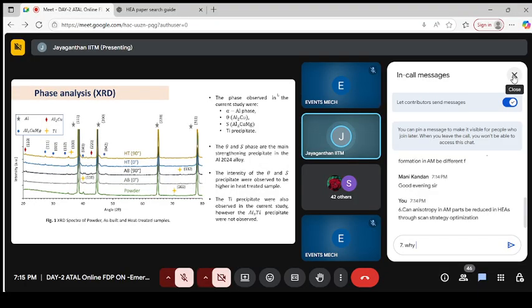And then if you do X-ray diffraction, you can see at the bottommost. We have seen the physical features. As I mentioned, the alloy contains aluminum plus other alloying elements. They have the powder. We did 3D printing. For the 3D printed sample, we have to do X-ray diffraction to see what phase it shows.